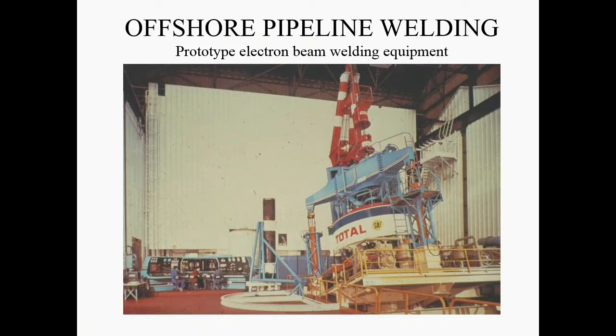So now the heat required for the welding is produced by an electron beam. For an electron beam to be efficient, you certainly need vacuum. So in order to carry out the weld, you need somehow to create vacuum around the weld. Because it's more difficult to enclose everything in vacuum, what they did in this prototype test: for the gun that produces the electron beam, you need generally very good vacuum. So they use a chamber with high vacuum for the electron gun, and a chamber with lower vacuum for the pipe.